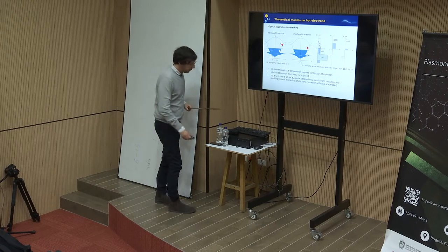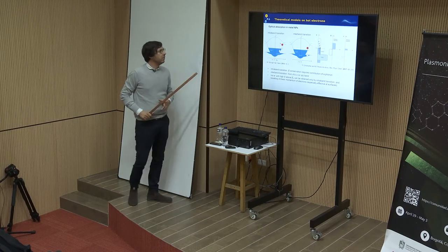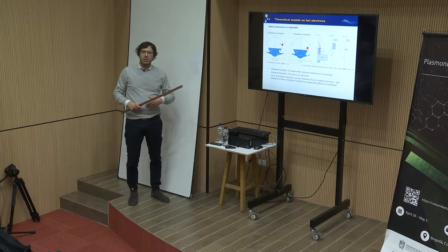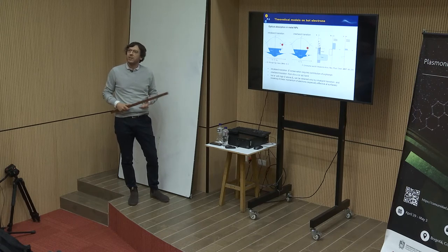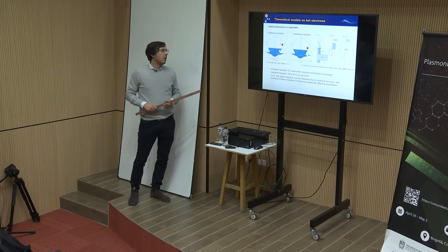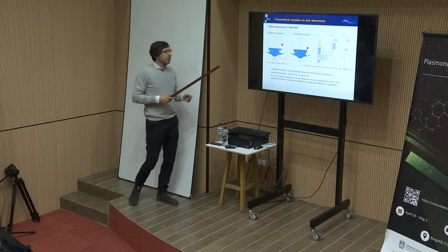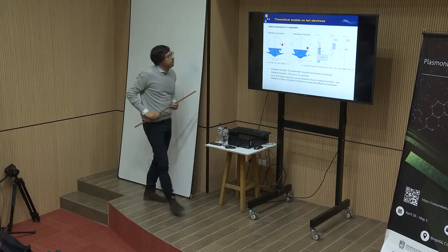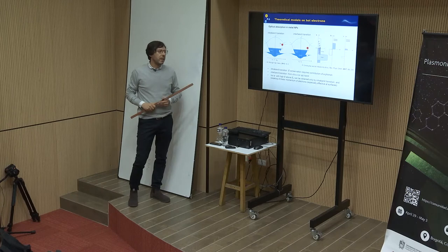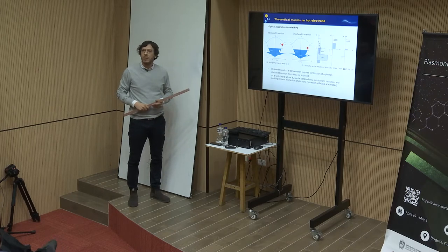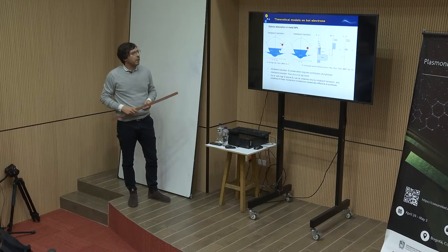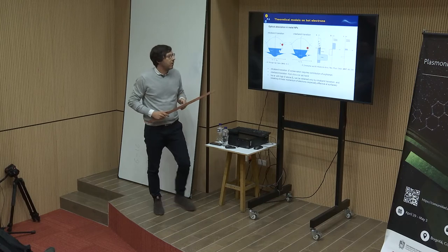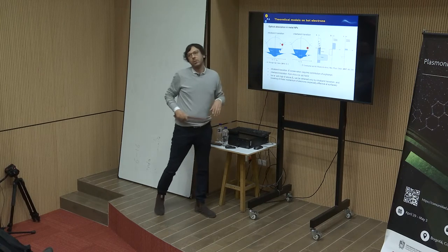Okay, this is just to talk about what is the difference between optical excitation and interband transition, and why these carriers are so hot, have such high energy, and we can use that in our applications. Of course, usually in noble metals, the d band is quite far below the Fermi energy, and so if we excite electrons through optical excitation, we will have the creation of electrons with energy around the Fermi level, while holes would be much more energetic.